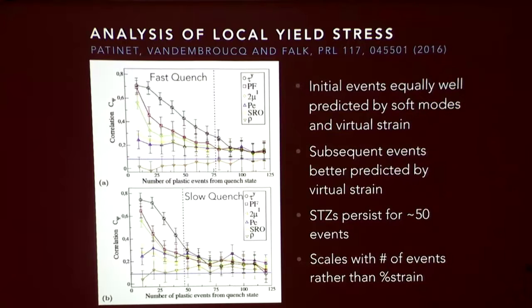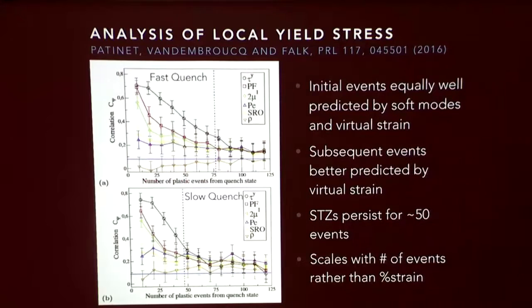Basically what this is saying is that you get quite good correlation with the initial structure out to 75 or 50 events, depending on the quench, for the participation fraction measure, and the other measures don't seem to do as well at predicting where you're going to get deformation, but they all except density seem to have some relevant information. It's not that they don't carry any information about where you're going to deform, it's just that they don't have the whole picture.